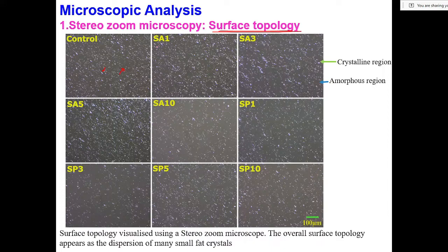crystallized fats. Okay, now if you see, in comparison to the control, in SA1, SA3 and SA5, as the emulsifier content was increased till SA5, this agglomeration increased, and also the crystal size was increasing. However, when we increased the concentration of the emulsifier at SA10, there was a marked reduction in this crystal formation. Okay, similarly, if you also look into this SA3, there are the agglomerations, you can see quite clearly over here. Okay, and this was again improved in SA5, however in SA10 it totally diminished.